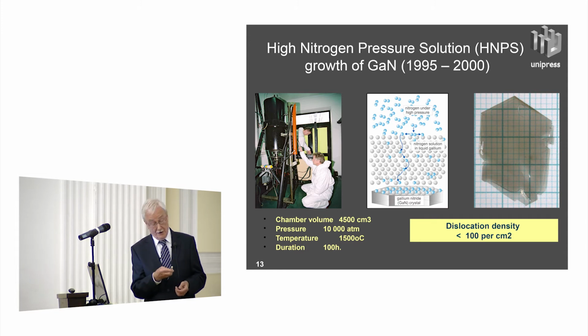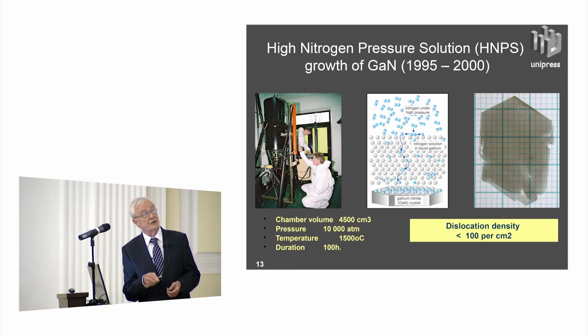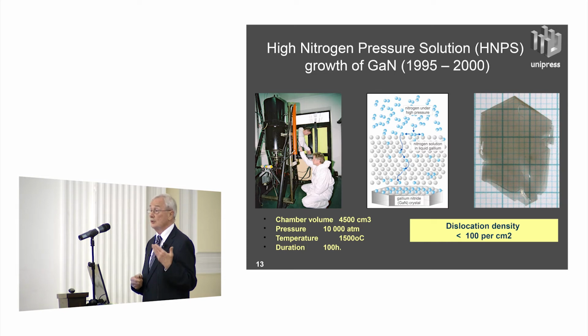I will maybe only briefly show that this picture shows the main idea of the process. So nitrogen under high pressure and high temperature dissociates, diffuses from the hot end of the crucible to the cold end, and the crystal is grown here. That's the equipment which was already shown by Professor Kossuth. And this is one of the first crystals which were already good enough for use as a substrate for homoepitaxy.